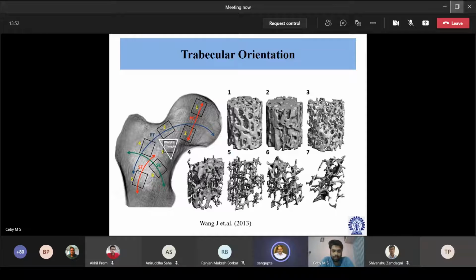The more solid it becomes, the orthotropy and isotropy merge and come closer to each other. So for macroscopic models, the isotropic assumption is reasonably proved to be acceptable within 5% error. That I will give you as a supportive paper later on.